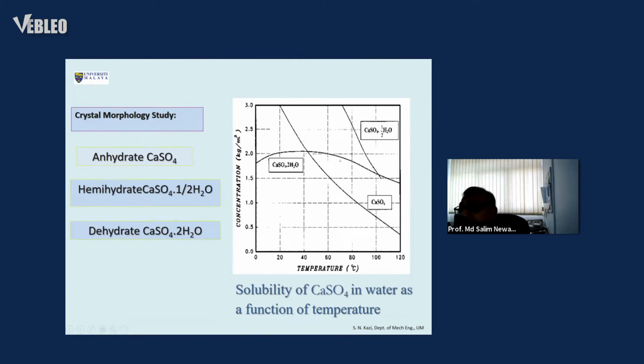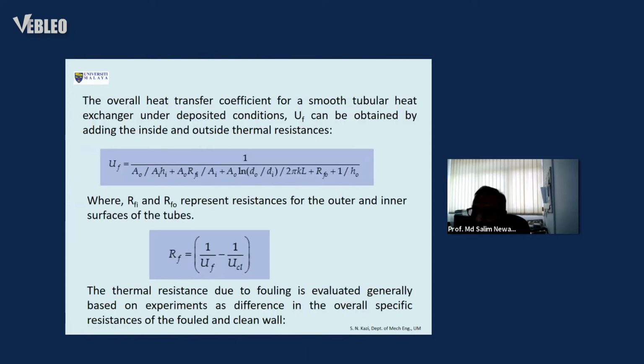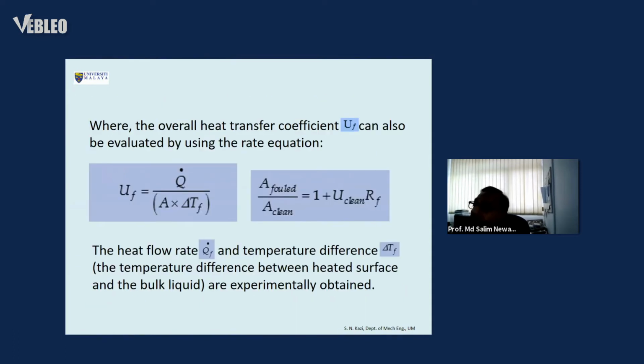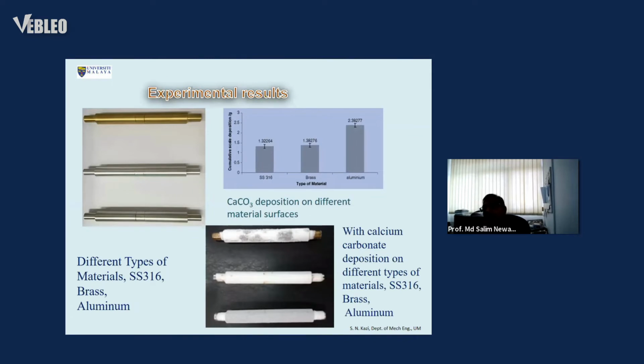And in this experiment, we can see that the solubility decreases with the rise of temperature. This is the calcium sulfate. So we move on further. These are the equations we use for calculating the heat transfer resistance and the fouling factor. In the course of time, when deposits form on the heat exchanger surface, we get this type of deposition, and the deposit changes depending on the thermal conductivity of the surface.